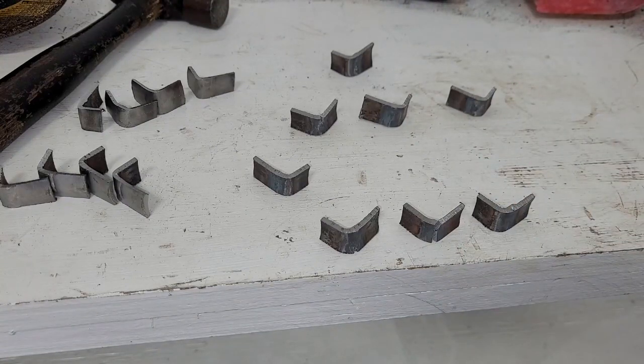So, my takeaway is that these welds are decent as far as strength. All of these passed in tension. And the backside is really just, to me, telling me that for the strongest possible case, I need to make sure I'm getting full penetration and actually getting a weld on the backside of the material. So what I was doing when I welded this, I was kind of going hot and fast. So I'm going to have to think about this.